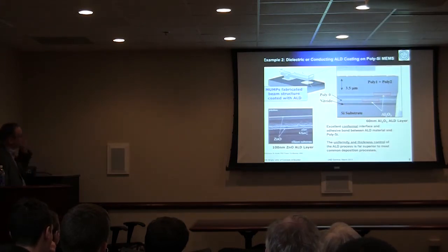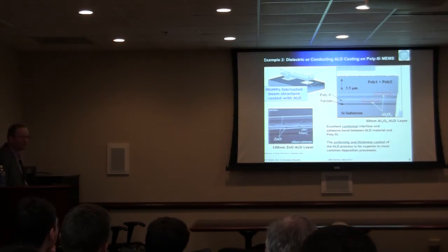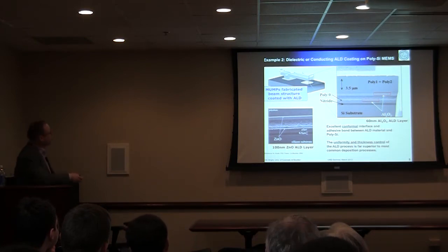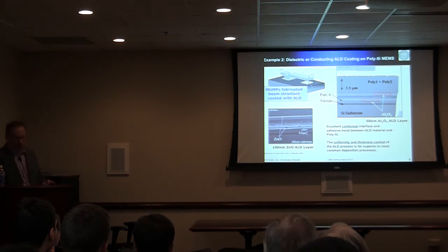But also one can work on dielectric or semiconducting coatings to control charge between the surfaces. So here is an example of a MUMPs device. This is a polysilicon beam made from a MEMS process, and two examples of ALD-type coatings. One is aluminum oxide coating, and one is zinc oxide coating, both by ALD. If you look at the cross-section of this beam, you can clearly see the coatings. So it's a conformal process. Aluminum oxide here is used as a dielectric coating. Zinc oxide is more of a conductive coating.